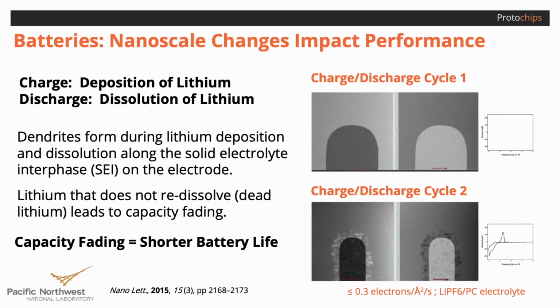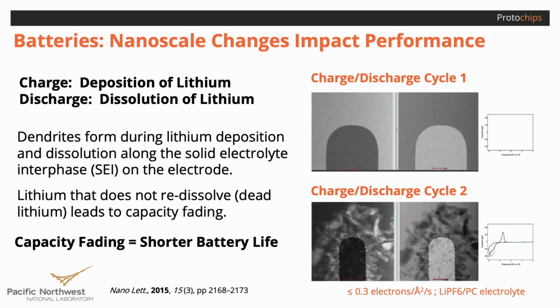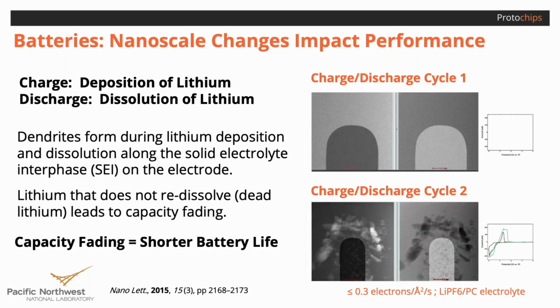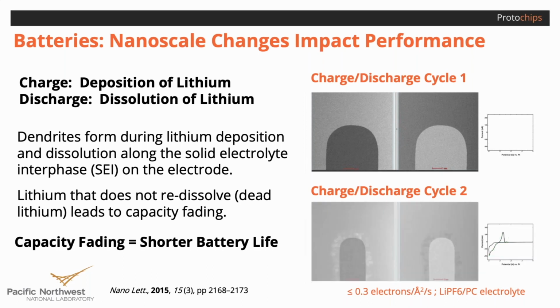Cycle 2 shows the second charge-discharge cycle for the same cell at a lower magnification. During the second charging cycle, even greater amounts of lithium become trapped on the surface of the electrode due to the buildup of dendrites formed during the previous charge cycle. This type of behavior is indicative of the structural changes that occur during capacity fading, since less lithium is redissolved into the electrolyte as the battery discharges, a shorter battery life results.